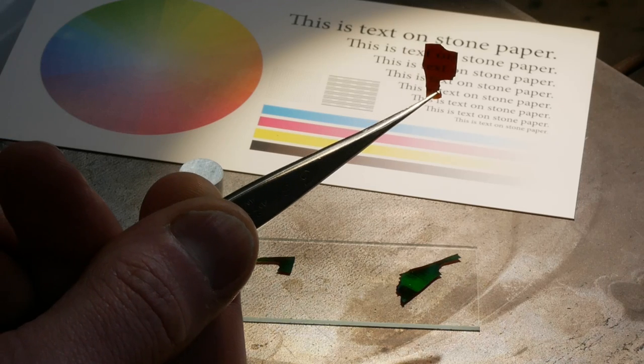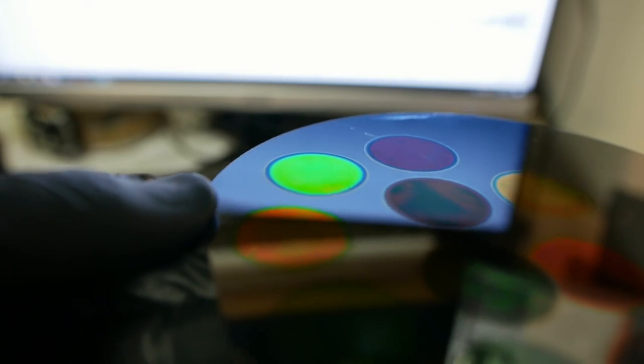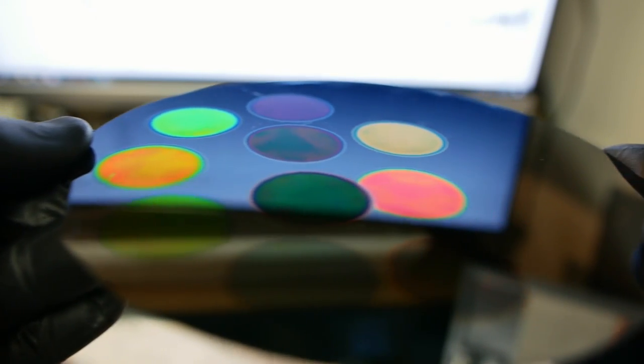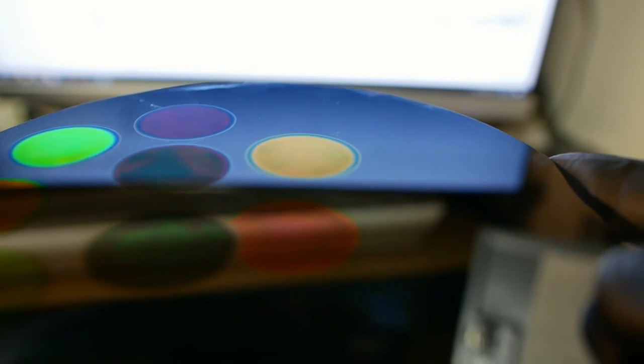And I should point out that porous silicon is not a perfect optical material. It actually absorbs a lot more blue light than it does red light. So it's actually difficult to make a blue rugate filter, even though it's still possible. It's not as efficient because the silicon is, in fact, absorbing some of the light. So unlike the theoretical discussion earlier, yeah, if your layer is absorbing certain wavelengths, obviously that's going to destroy the energy, convert it into thermal energy. It's not going to be perfect.